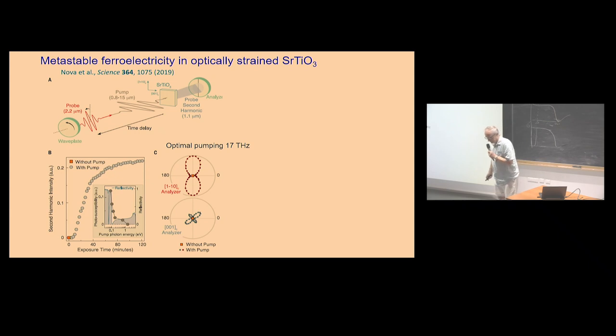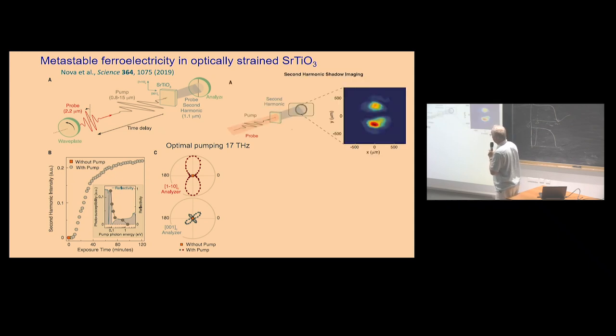I have here another paper from the literature, 2019, Science. Again, the Cavalleri group. They investigated strontium titanate, and they pumped it at different frequencies or different wavelengths and probed it with such a beam, and they observed second harmonic generation. Strontium titanate is not ferroelectric; it's a centrosymmetric system. I will speak about it more in the next slides. Let's say they pump it at low temperatures, but anyway, it's not ferroelectric. But they finally observed two domains in second harmonic generation. So it looks like a ferroelectric.